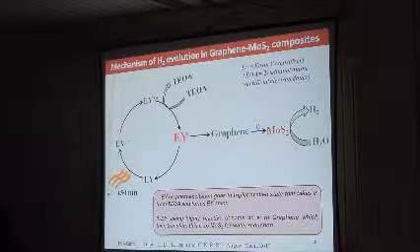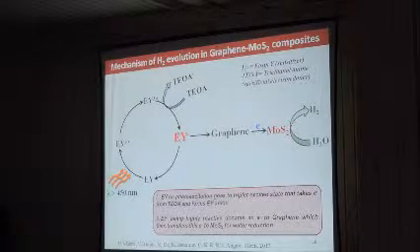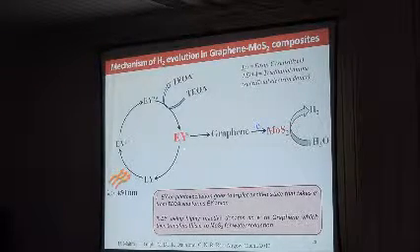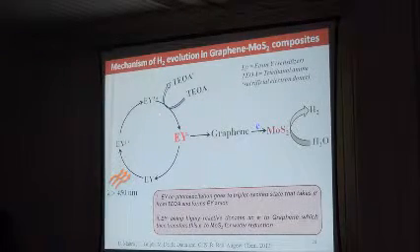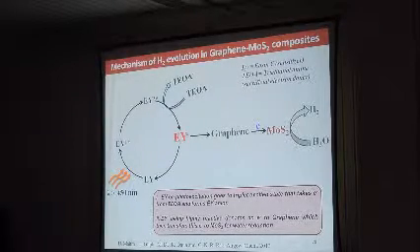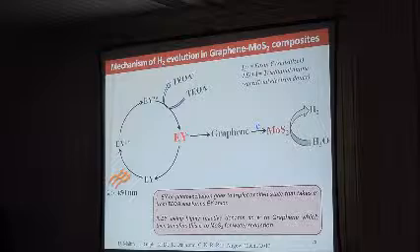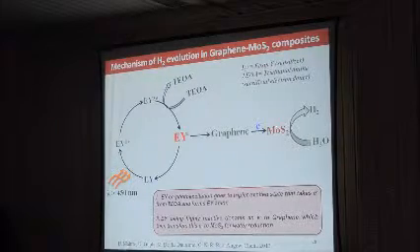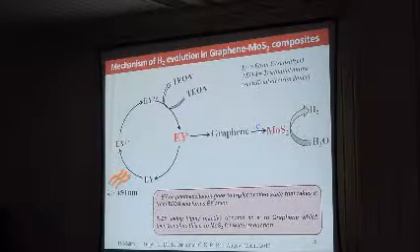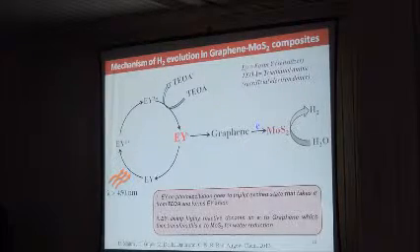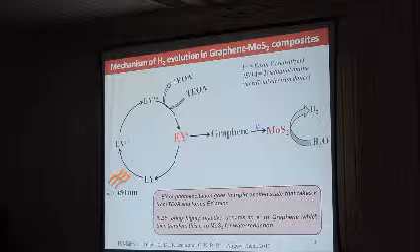For example, we have done dye-sensitized production of hydrogen using MoS2. Use an eosin dye, excite the electron, go to the triplet state, then it picks up an electron from an amine, triethanolamine, and becomes a negatively charged species that is very unstable, that gives away the electron to MoS2. I've used graphene as a channel for electrons, and this electron reduces the proton to hydrogen. So this is the kind of thing we used.